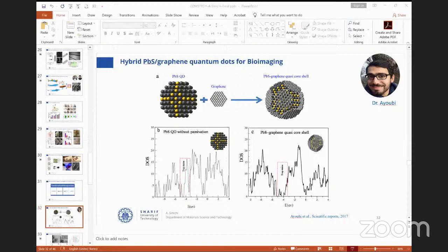As you know, lead sulfide is a wonderful photoluminescence material. However, lead is very cytotoxic. And we cannot modify the surface with hydrogels, with polymers, or even with metals, because if we put in metals, we lose the photoluminescence. If we use a polymer, anyway, lead will diffuse from the layer and make it cytotoxic. One idea is to coat it, to cover it with a thin layer of graphene.